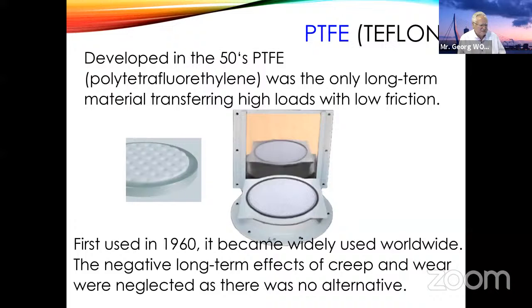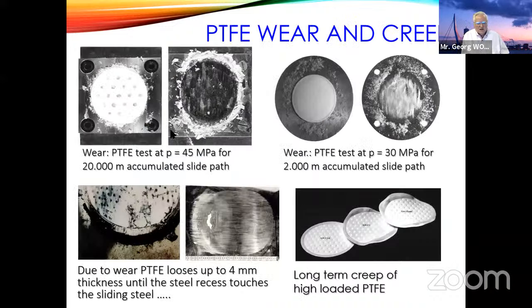When we look at the tests, you see here we have a PTFE test with 45 megapascal for 20,000 meter accumulated slide path. And we have to say the PTFE is not looking good, but it's still alive. And 20,000 meter is a very high number. On the right side, we see a test of a non-dimpled PTFE. Normally the PTFE has the dimples with the initial greasing and lubrication, but in the guides you use it without the dimples, and this is already after 2,000 meters, heavily worn out.